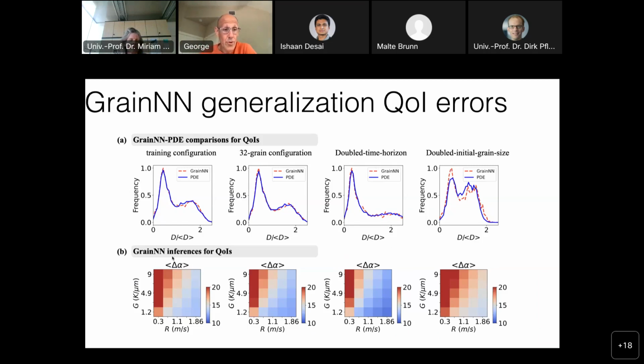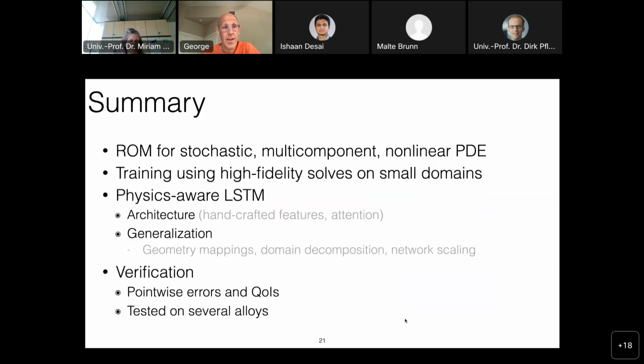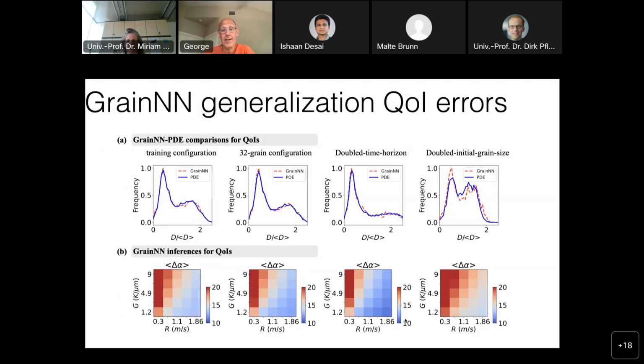And then we can also see average misorientation. So this is only inference. We don't compare with ground truth because the calculations are very expensive. And so then once we have the GrainNN, we can look, let's say, at what is the average orientation for different parameters and create these maps that can go then to the downstream tasks for residual stresses. And that really makes these calculations feasible. It would take days to do it using phase fields, and now we can do it basically in seconds.